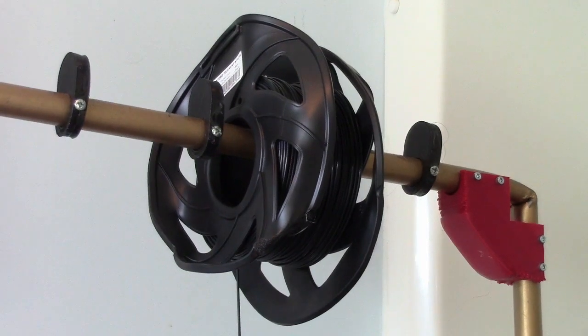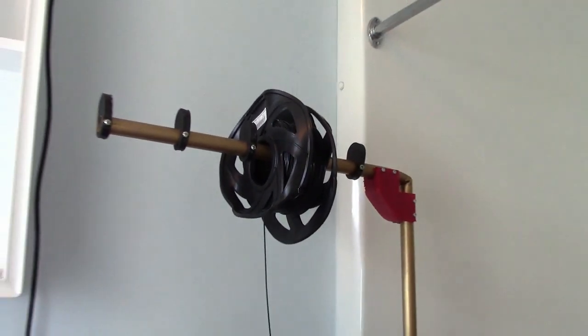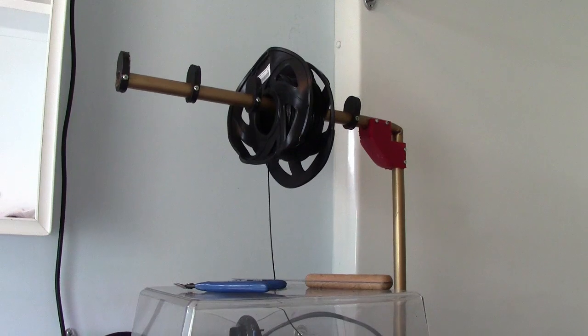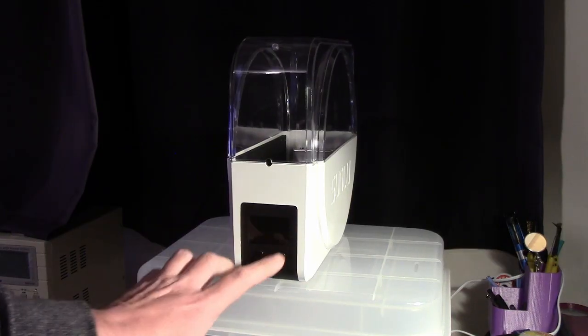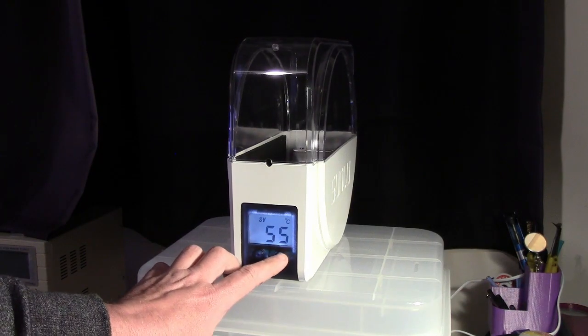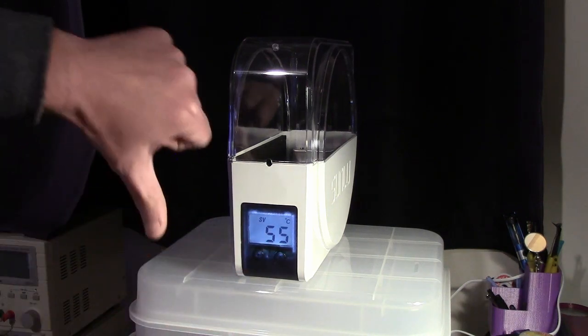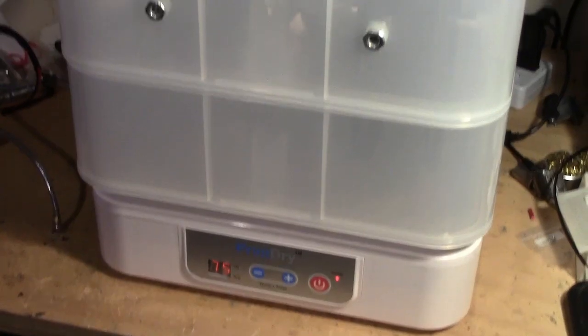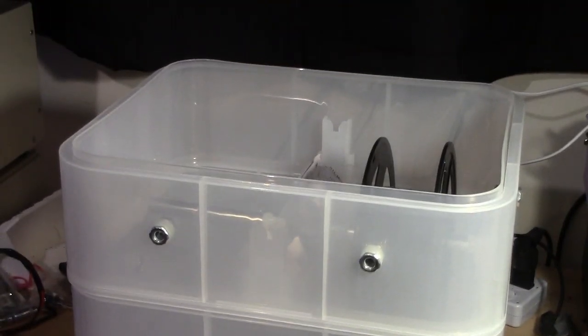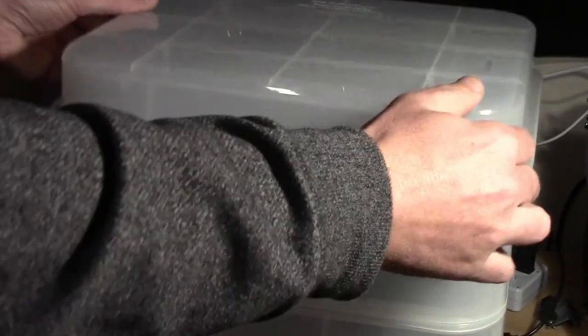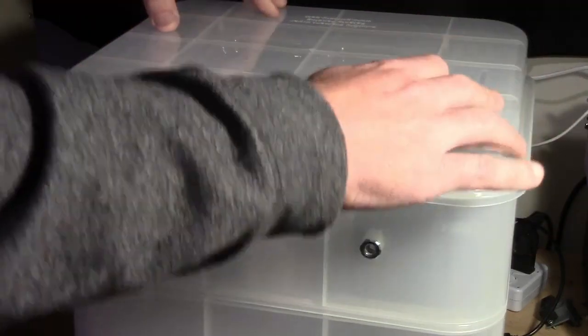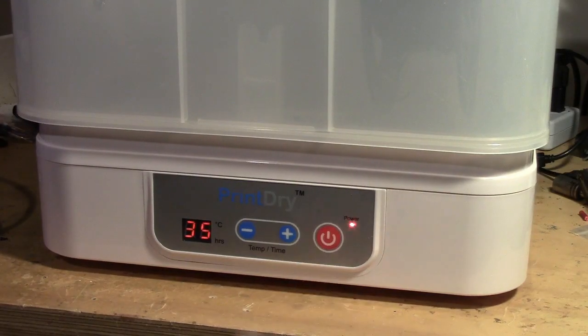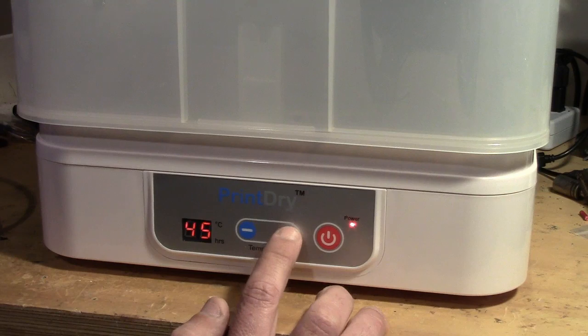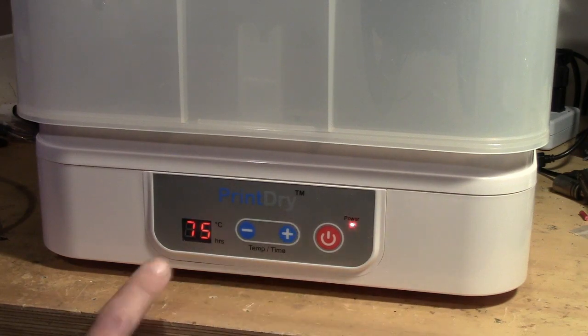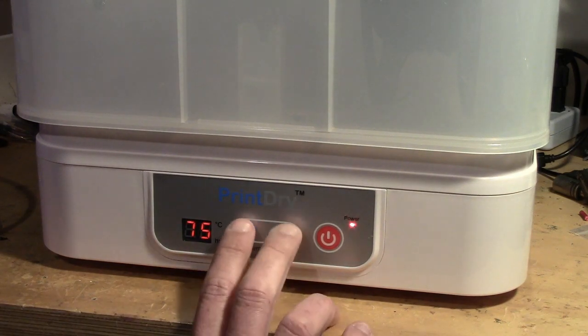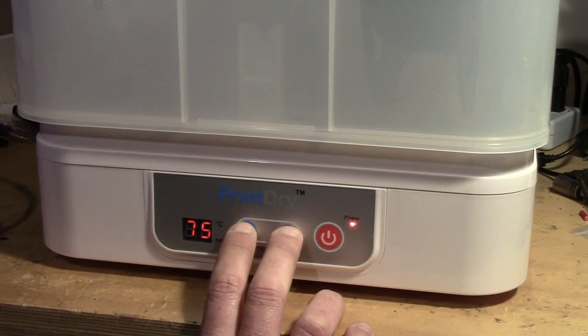You can try drying the filament in a normal oven, although you're just as likely to deform the spool and make a mess. This is the first filament dryer that I bought, although the maximum temperature was only 55 degrees, which isn't sufficient for drying nylon. The thing that really improved the performance of my nylon prints was that I recently bought this Print Dry Pro. This is able to heat at up to 75 degrees, and drying the filament for 12 hours at that temperature is enough to drive the moisture out of the filament.